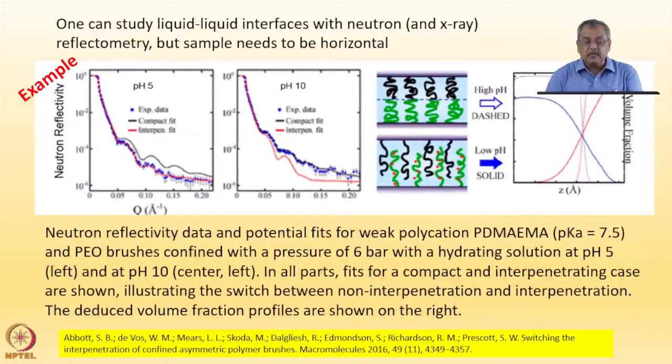But in the case of neutrons, the interesting thing is that I discussed with you earlier that we can play with the D2O-H2O ratio in the solution, or if it is water, then in the water background or the water substrate on which we spray these chemicals, so that I can get a very good contrast. That is the advantage. So here I am just showing you one example of neutron reflectivity data for weak polycation